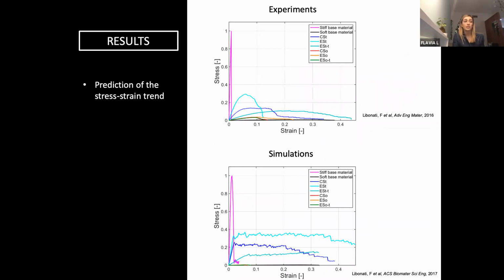What is interesting is that with this kind of approach, as I said before, with finite element, you can really predict the exact properties, but this was not our goal in this case. Our goal was to understand the role of the toughening mechanism on the overall behavior and try to predict which was the best topology. And in this case, we can have a great comparison between experiment and simulation.